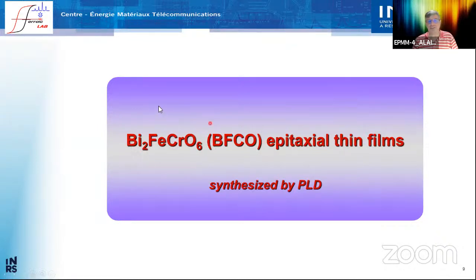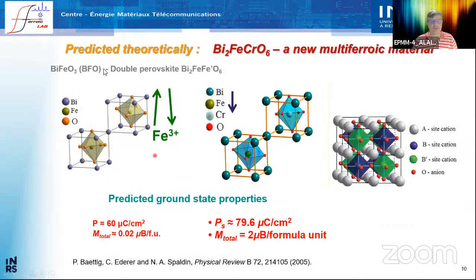So bismuth ferrite, BFCO, bismuth iron chromium oxide, epitaxial thin film synthesized by PLD. As I said before, this material, BFO, bismuth ferrite, was one of the only ones considered multiferroic at room temperature until very recently. And Spaldin and co-workers, by doing simulation, predicted theoretically that if you replace one of these irons with a chromium, so now you have iron, chromium along the 1-1-1 direction, then this material, which is actually a pretty good ferroelectric but a pretty lousy magnetic material with only 0.02 Bohr magneton per formula unit, could actually become much better, magnetically speaking.